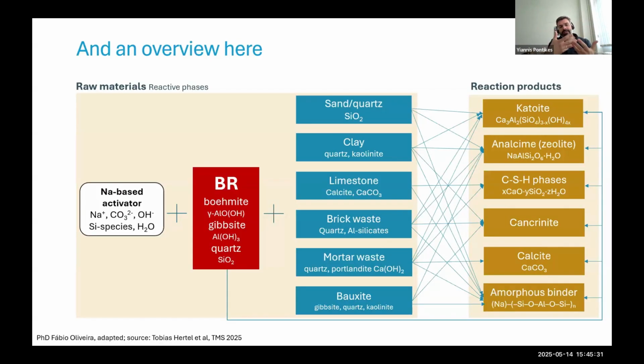So depending on what you add, you create, let's say, different reaction patterns for things to grow. And if you know what you want, for instance, if you want more analcime or more katoite or more CSH phases, you can steer the reaction accordingly to this or the other direction. And that's interesting. Because again, we add 80% of BR, 20% of wastes or things that not many people want, and we create a product that actually can find an application in the market.